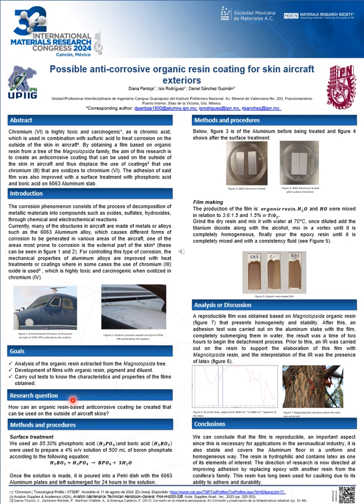Methods and procedures. To carry out surface treatment, phosphoric acid at 85.3% and boric acid were used to prepare a 4% w/v solution of 500 ml of boron phosphate. Once the solution is made, it is poured into a petri dish with the 6063 aluminum plates and left submerged for 24 hours in the solution. Below, you can see a photo of the aluminum before being treated and after surface treatment. It is visible that the surface treatment cleaned and whitened the aluminum slabs.